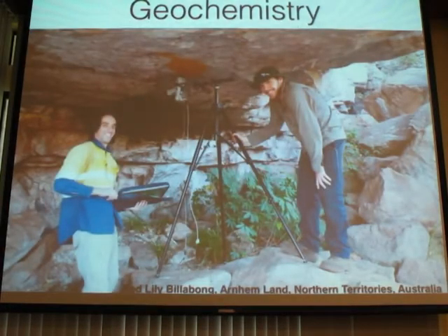These are a couple of my colleagues from ANU — Christian on the left and Jacob on the right. What they're doing there with their Star Trek ray gun is shooting X-rays onto the rock art to determine the elemental makeup of these pigments, which has some useful applications. We've found that not all black drawings are necessarily charcoal — they may be manganese. So if you're thinking of sampling charcoal for rock art, we've got to make sure that it's really charcoal. PXRF might be a very good way to determine whether samples are worth sampling from the art.